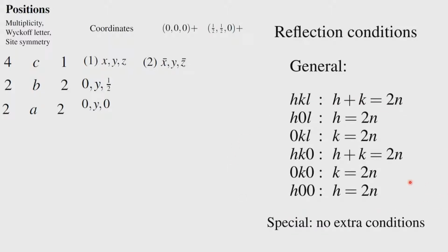Now, these additional systematic absences are not going to complicate your space group, because the crystal system is monoclinic. You have already determined a, b, c, alpha, beta, gamma. You have determined also that it is a C-centered lattice. So, C centering gets the preference. So, it is always the centering of the lattice which gets the preference, that means the Bravais lattice information gets the preference over and above the glide plane systematic absence, and over and above comes the screw axis operations.